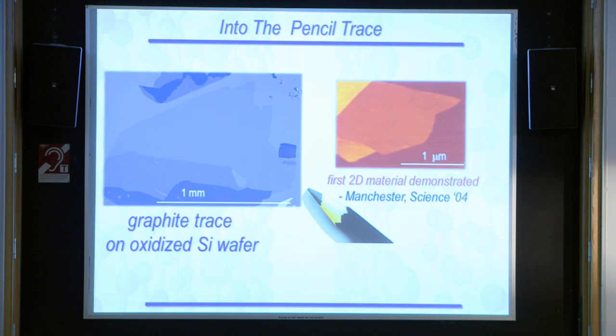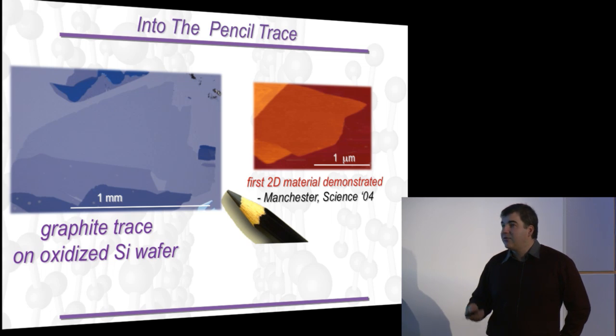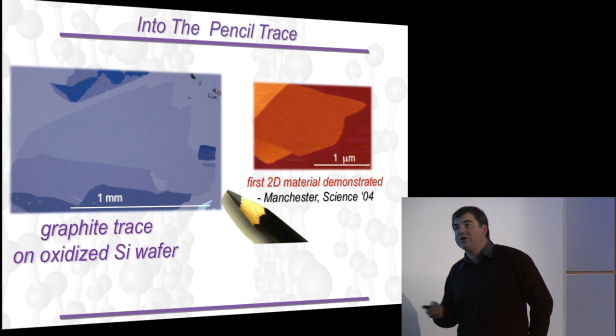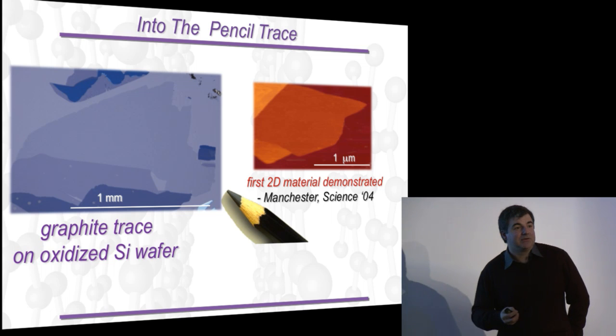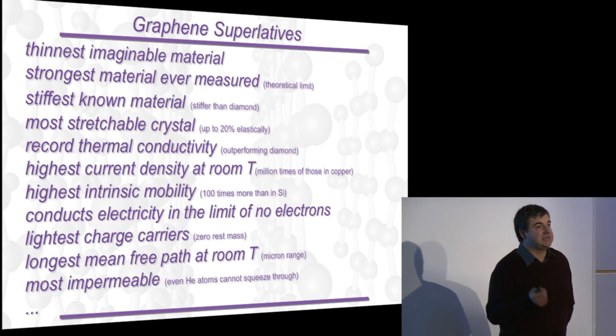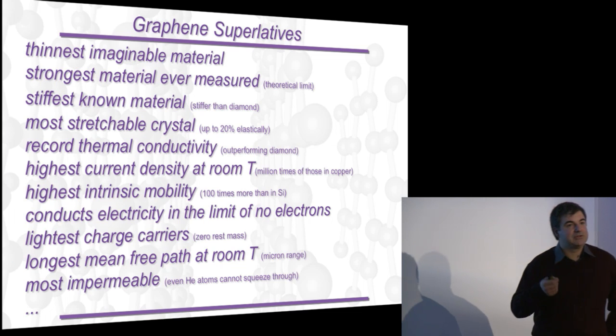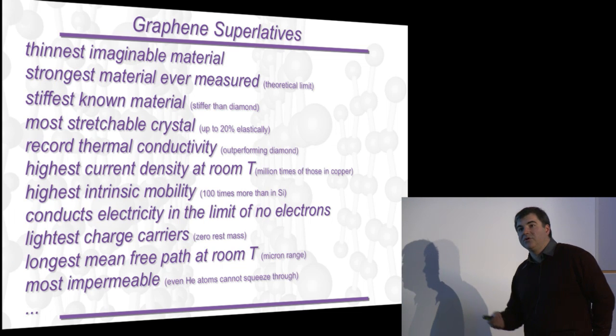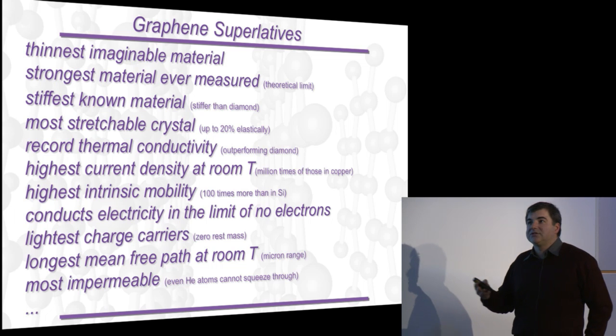But our days were quite good at our scribbling, and we can exfoliate millimeter-sized crystals without any problems. So immediately after people isolated it, we jumped into the research of those crystals, and quite a number of very interesting and very unique properties have been discovered. Of course, it's the thinnest possible material, the strongest, the most conductive, the most thermally conductive, the most impermeable, the most elastic, and so on and so on.